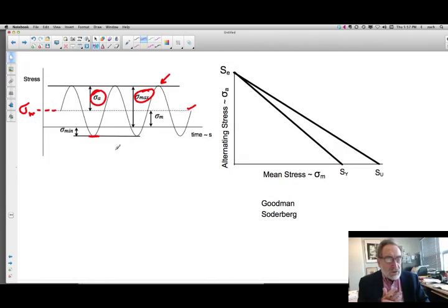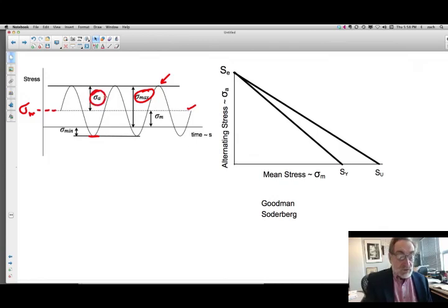So what we do in order to figure out how we're going to know if this is our state of stress, whether it's going to fail or not because the mean has changed. There's more than a couple ways, but two main ways of looking at this is to use these curves. We plot on the vertical scale the alternating stress, which is this one over here, and the mean stress here, which is this one.